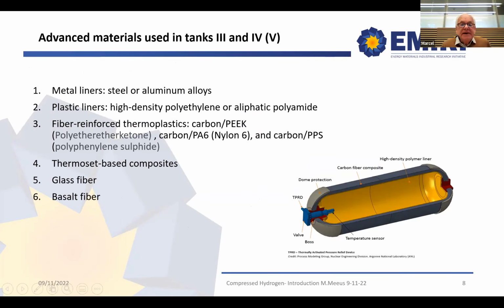So we are at EMIRI's advanced materials. What are the advanced materials used in compressed hydrogen storage in the types 3 and 4? The metal liners being steel, but mostly or generally aluminum alloys. The plastic liners as the barrier being high density polyethylene or aliphatic polyamides. For the outer wrap, fiber reinforced thermoplastics, and that can be carbon PEEK, polyether ether ketone, or carbon PA6, that's a nylon composition, nylon 6, and carbon PPS, and that's a polyphenylene sulfide. So these are the different reinforced thermoplastics wrap materials. There are also thermoset-based composites, glass fibers, and basalt fibers.